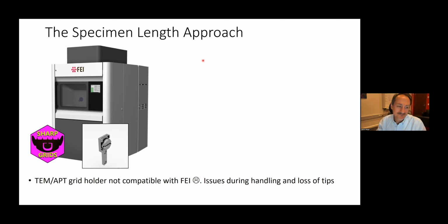No worries. So I was saying basically on this slide that we used the TEM at Curtin, which is an FEI Talos, and the grid holder and the tungsten grids from Sydney. The issue with that process was that we had to take the grids out to put them in our TEM holder. And in that process, we lost and damaged too many tips. So this was not a really good way to do it at the large scale.